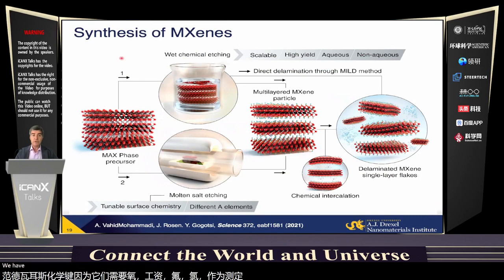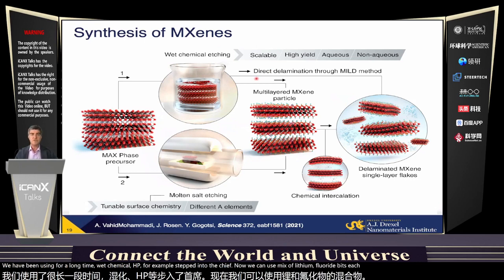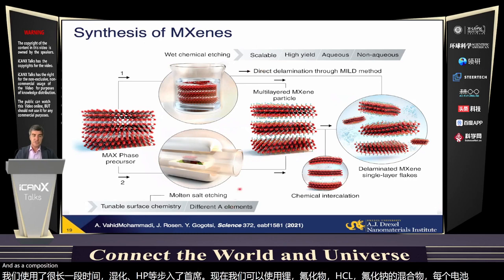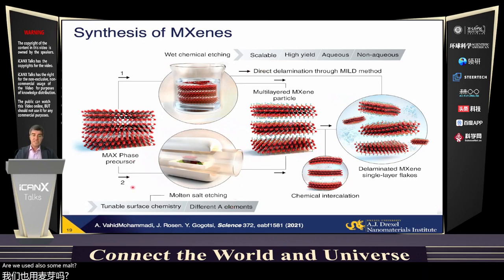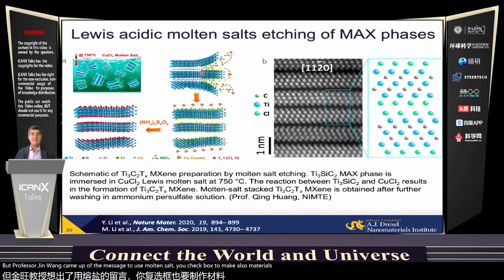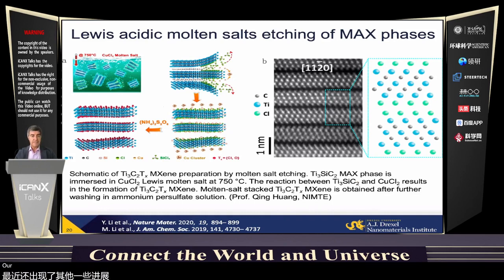We have been using for a long time wet chemical etching, for example, starting with HF. Now we can use a mix of lithium fluoride with HCl, sodium fluoride, HCl, and other compositions here. We used also molten salt for producing nitrides, like titanium nitride MXene. But Professor Qing Huang came up with a method to use molten salt eutectics to make also materials with different termination, for example, like chlorine or bromine on the surface here. And there have been also other developments very recently showing wet chemical chemistry or synthesis from organic solution using chlorine, bromine, iodine, other etchants here. So there are many ways.